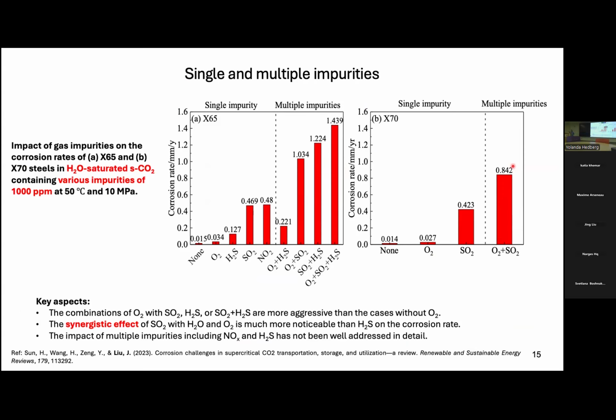For the corrosion immersion test results, we look at single impurities. The "none" refers to having only water. So you have CO2, and you must have water to have corrosion. If you don't have water, then even though you have other impurities, the damage will be close to nil. Now, based on the current results, we noticed that NO2 is more aggressive than SO2, more aggressive than H2S, and then oxygen, and then just pure water.